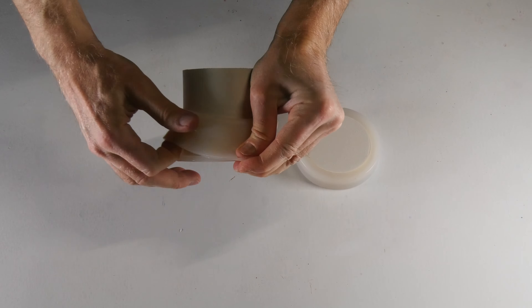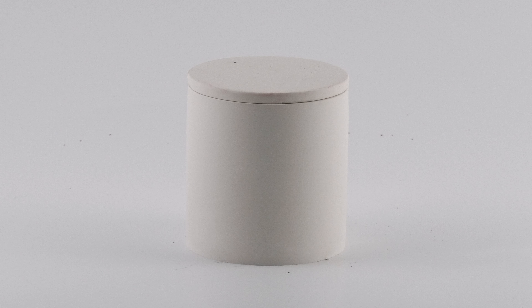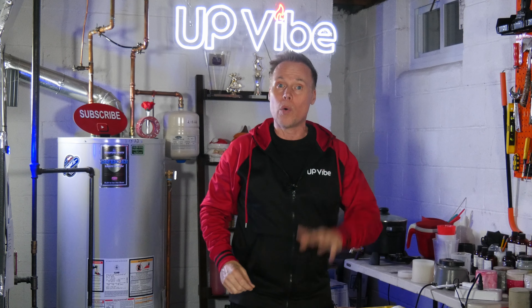30 minutes later, I'm ready to demold my white concrete candle jar made with hydrostone. Hydrostone is a mixture I use quite often — it's an awesome product, as you can see by this beautiful white candle jar. Similar to hydrocal, calcination is a concern depending on how you manage your max surface temperature. My jars rarely go over 140 degrees by design, and I use EarthSafe Finishes Sealer to protect the jar. If you're a responsible candle jar maker, hydrostone is a great option. Three things I love: the quick demolding time, the relative strength, and the overall cured weight.